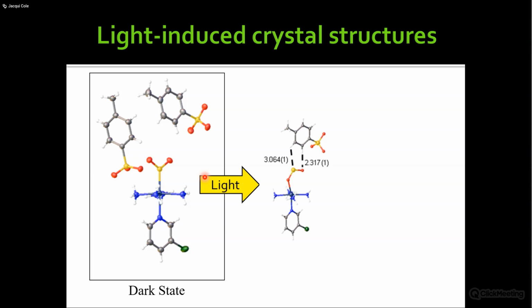And when you cool down this particular complex to 100 Kelvin and you apply green light to it, so that's at about 520 nanometers, then you tend to get in this case the oxygen-bound sulfur dioxide. So it went from sulfur-bound to oxygen-bound. And then what you see here, because of this reaction cavity, right? So if it goes to the oxygen-bound, that's quite a big change while keeping everything in the single crystal. And you see the other oxygen that's not bound is sticking out. And because it's now near this counter ion, that becomes quite uncomfortably close for this counter ion, right? So that presents a very steric